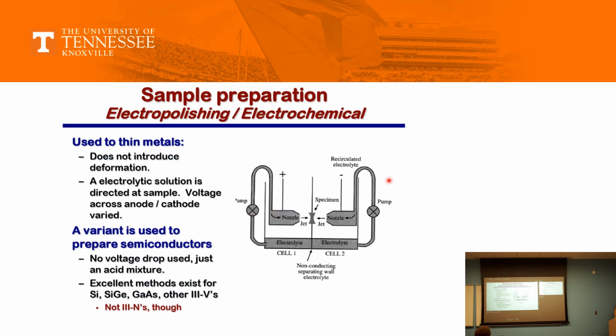Now, this is a classical example we have in our lab, where I created a dimple and I put my sample here, and I give all those chemicals which we talked about in the first slide. That is basically an electrolyte that is inserted through these pipes. It's a very easy configuration. You have a bath here, you have a pump and a pipe, and a thin jet that goes onto your specimen. Very simple. So two things that you can also DIY at your home. And you have the acid, and with the nozzle size, you can control the jet. And slowly you start eroding the material from here.